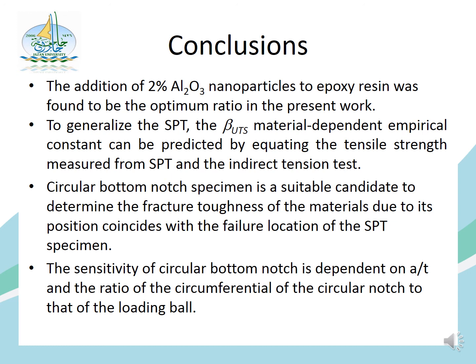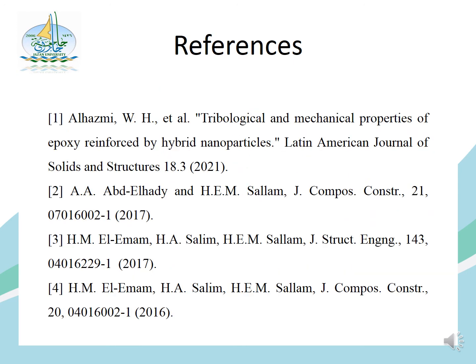For the second main objective, we can see that the circular bottom notch specimen is a suitable candidate to determine the fracture toughness of the material, due to its position coinciding with the failure location of the small punch test specimen. Finally, the sensitivity of the circular bottom notch depends on the A to T ratio, which is the crack length to the thickness, and the ratio of the circumference of the circular notch to that of the loading ball. Those are the references for our study that conclude this presentation.